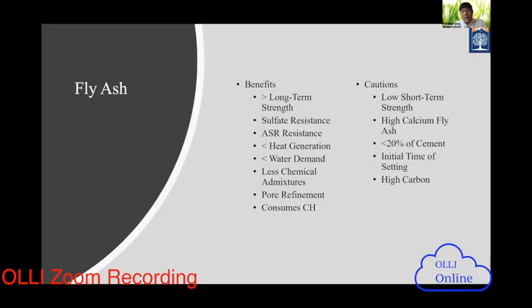So heavy benefits are there, as you can imagine. So what are the benefits? It provides long-term strength, as we talked about. Short-term strength could be a little bit lower than even cement, original concrete, but long-term strength will be really high. It provides resistance to everything, like sulfate resistance, ASR, less heat generation, less water demand, and it needs less chemical admixture. Pore refinement we talked about. It fills up the void, so that's a big advantage, and it consumes the calcium hydroxide. So those are the heavy advantages. It's becoming impermeable concrete, easy to deal with, and provides protection, not only corrosion, it's sulfate resistant, yes, everywhere.